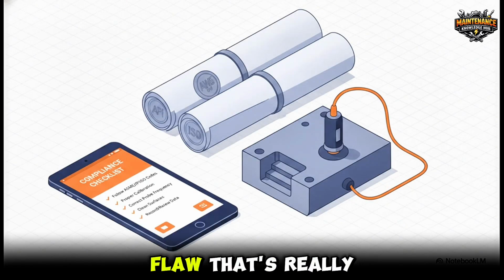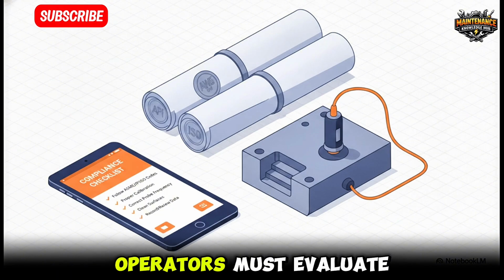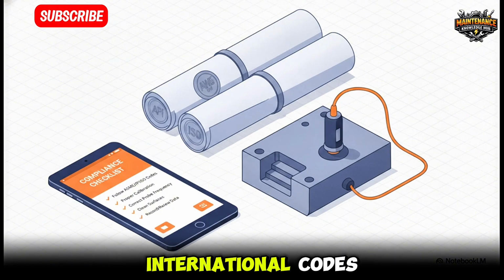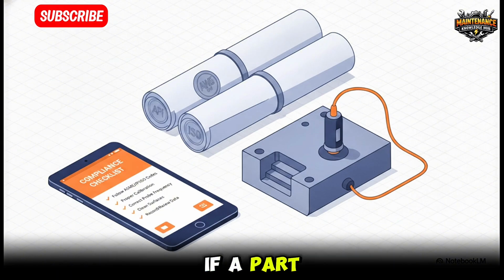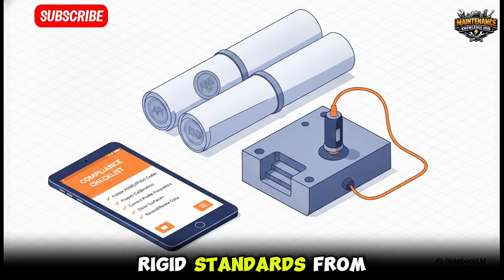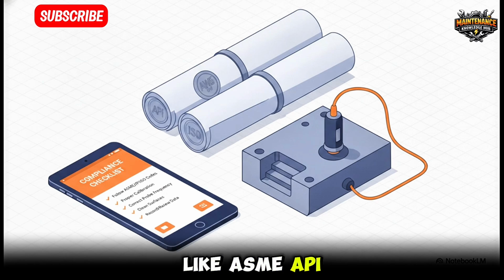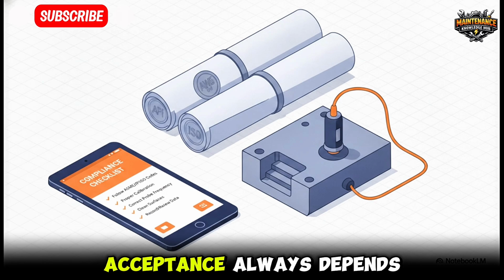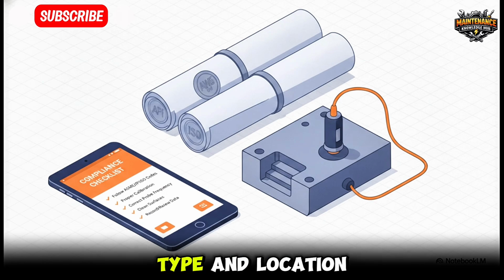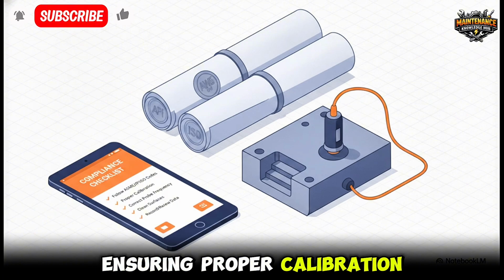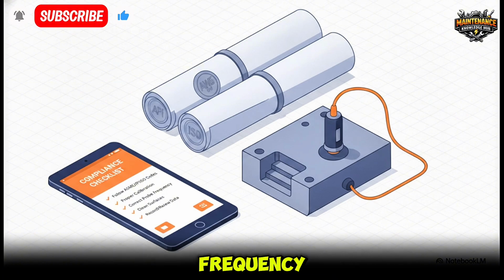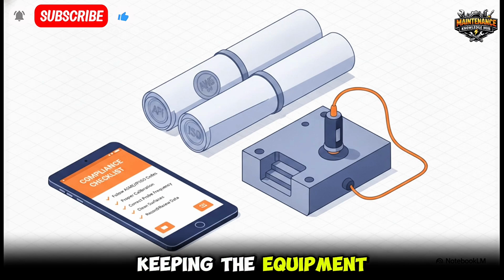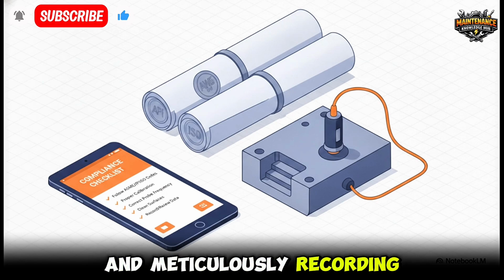And finding a flaw? That's really only half the job. Operators must evaluate their findings against strict international codes to ultimately decide if a part is safe for use or if it belongs in the scrap heap. They rely on rigid standards from governing bodies like ASME, API, the American Welding Society, ISO, and ASTM. Acceptance always depends on the specific size, type, and location of the defect. Safety also means ensuring proper calibration, selecting the exact right probe and frequency, using sufficient couplant, keeping the equipment in good condition, and meticulously recording the data.